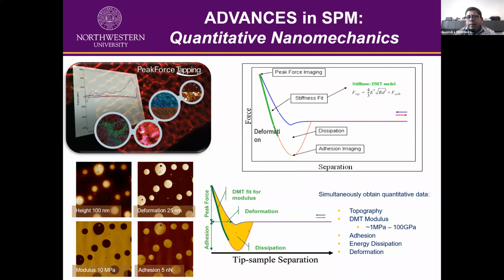A lot of users are using it, and this is especially popular for monitoring cell dynamics in real time. All living cells are dynamic, changing shapes due to the rearrangement of their cytoskeleton scaffold, and spreading and migrating on the cell culture substrates. So these processes and the mechanical changes that accompany them can be monitored with peak force, because the forces between the tip and sample are in the piconewton range as compared to nanonewtons in the tapping mode. So you are exerting a pretty low force on the sample, which allows you to measure the mechanical properties of the biological samples.